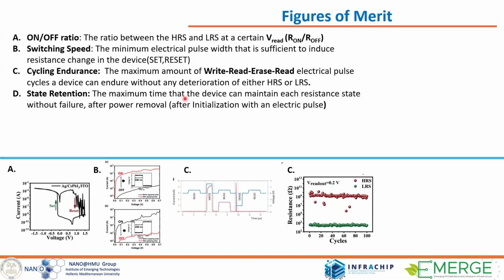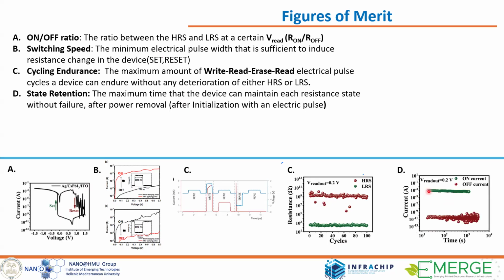Then another parameter is the state retention. So if you put the device, for example, at a low resistance state, how many seconds can it remain there without changing any bias of the device. This is endurance, this is retention. So this is the retention for the low resistance state, and this is for the high resistance state. Of course, the longer the retention, the better memory device we have. So these are the standard measures that we implement to evaluate the performance of non-volatile memristive devices: the ratio, the cycling endurance, the state retention, and the switching speed.